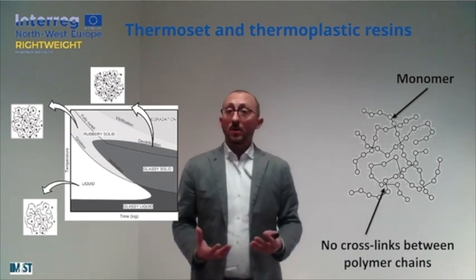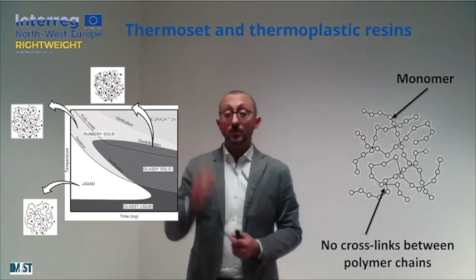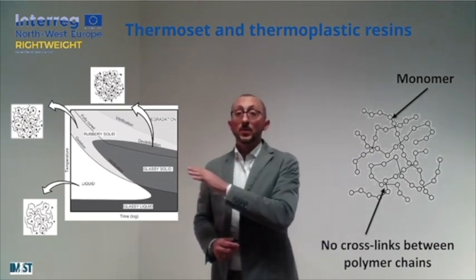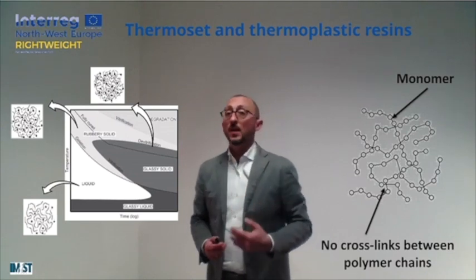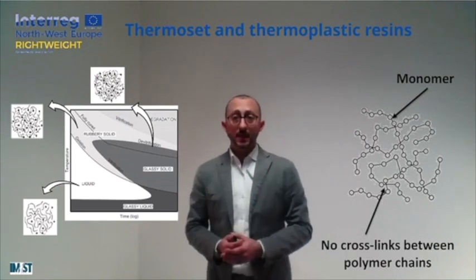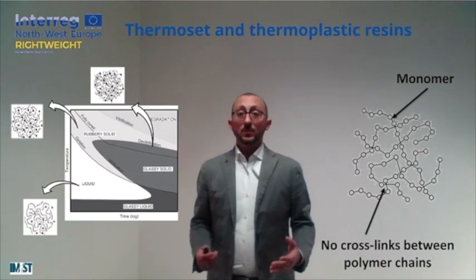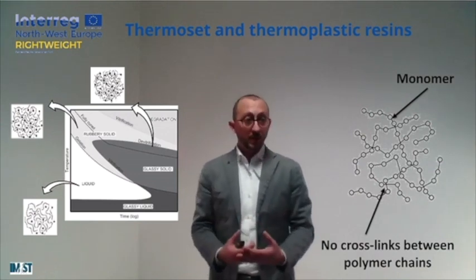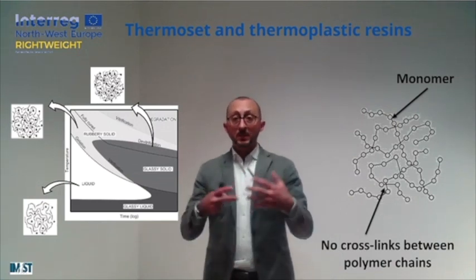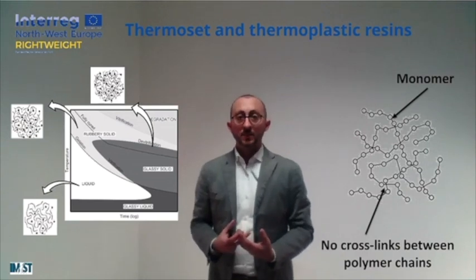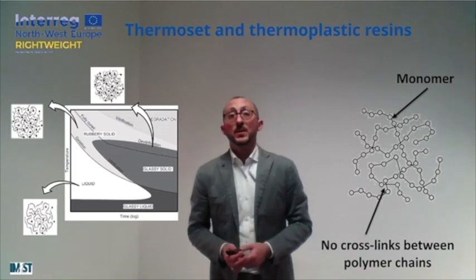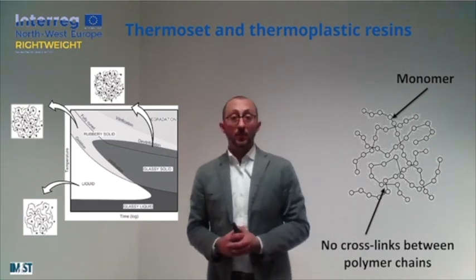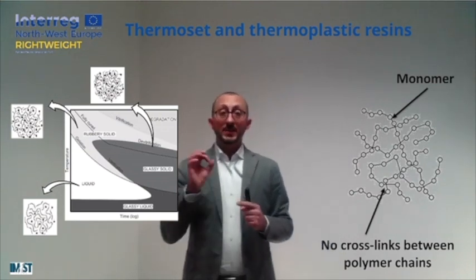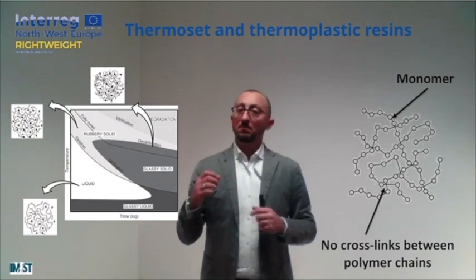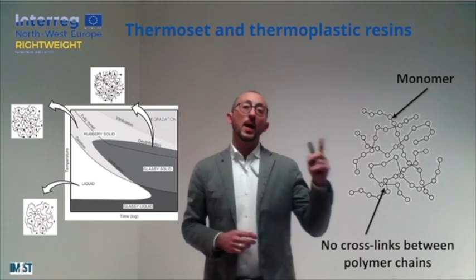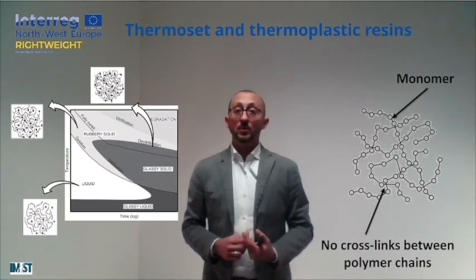And our way of understanding what is going on during the curing reaction is depicted in this graph here. If we imagine that at the very beginning we are starting with our resin system at some temperature in liquid state, and the conditions are suitable for the activation of the curing reaction, this combination of monomers will start. Our measurement of the curing reaction is given by the so-called degree of cure. The degree of cure will range from 0 to 1.